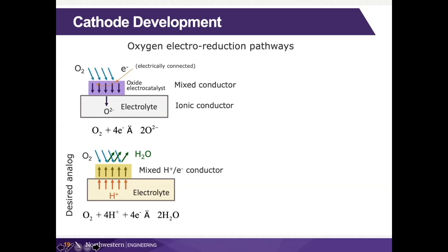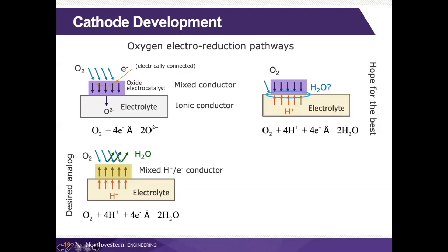In the case of a proton conducting system, then we'd want something which is a mixed proton and electron conductor. Again, this should be an arrow going forward and reverse, allowing us to do both electrolysis mode as well as fuel cell mode. Well, that would be the case we want. But in general, what people have used is this exact same material as we use in the oxygen ion conducting system. And there's some fear, in fact, that you might make water right here. If you use that material, the protons would come in, the oxygen ions would come in, the electrons would come in, and you'd make water at this interface, which would be very, very bad news. But you might try it and hope for the best.